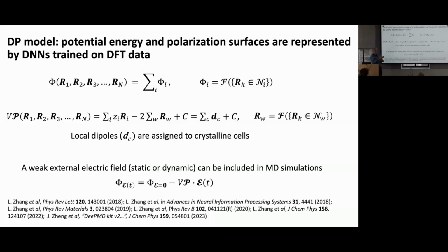In fact, in systems like the one that I'm describing here, these maximally localized Wannier functions are always associated uniquely to a certain atom. So these are just the displacement of the center with respect to the atom, and the displacement of the center with respect to the atom is learned from the maximally localized Wannier representation.